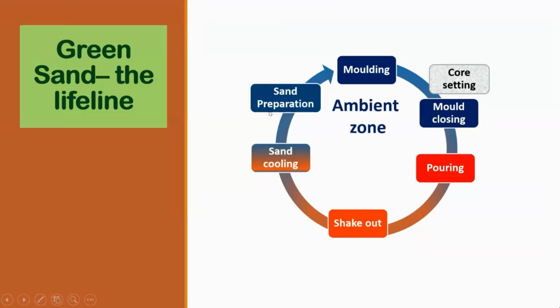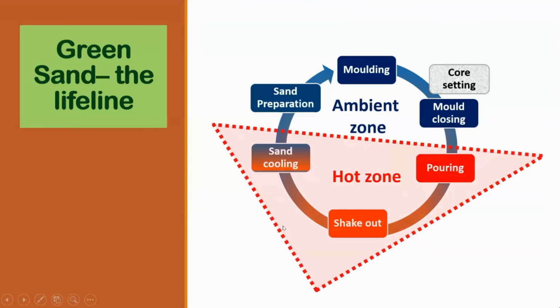Now in this, you will notice the blue zone, which is an ambient zone, and the red zone, which is a hot zone. Hot zone is where you pour the molds, shaken out, and then goes up to the sand cooling. Rest of it is the travel in an ambient condition. So this is a hot zone. Now, in the hot zone, a lot of things happen. And in the ambient zone, we repair the whole sand system back to its green state and then get ready for the next pouring operation.